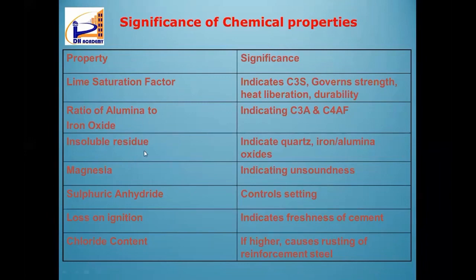Nowadays, I get so many calls, and in fact 2-3 webinars and a panel discussion were also organized in this manner, because after the lockdown, cement is old by 1.5 months, 2 months, maybe more than that. So what will happen to that cement? How can we immediately assess whether the stock cement is good or not? There are some conventional physical methods. Other than that, what I proposed is the loss on ignition test. It indicates the freshness of cement. It is a very simple test that gives very fast results. It indicates whether prehydration happened or not.